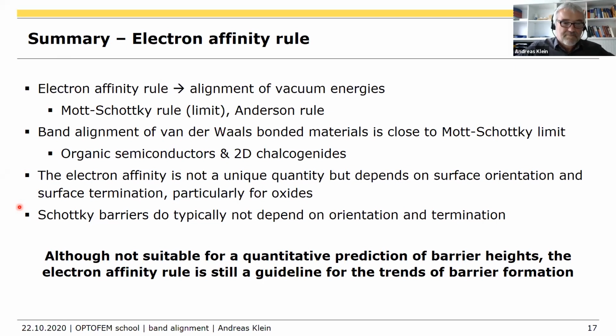That's a thing. In ceramics, in oxides, you can go to doping which can be much higher than 0.1%, so you can go to 5%, 10%. Then of course you change your density of states, you change your band gaps, and you have to consider that. At the very end, if there is time, I will show the experiment we made also with Mariona's sample, and that will be one example for this. Okay, good.